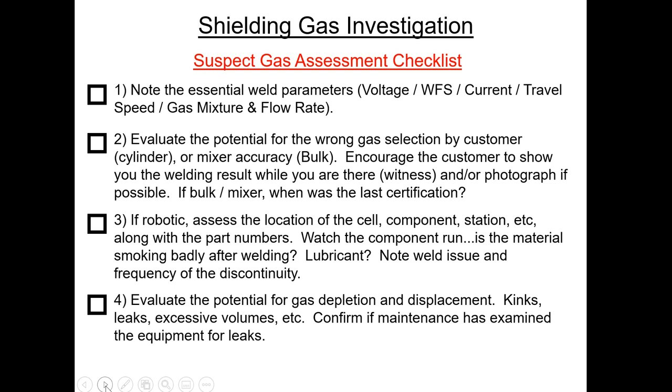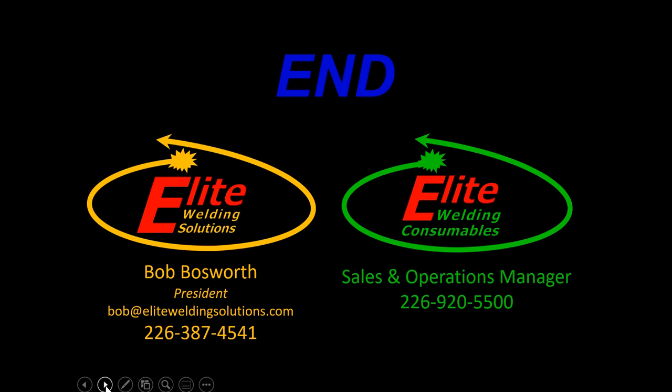And keep in mind that a leak is not porosity. A leak is a lack of gas, which could lead to porosity. But air cannot get back in, cannot defeat the pressures that are on the other side of your shielding gas system. So don't believe it when some people say, well, there's a leak of gas there, so probably air is getting in. No, we only live under 1 bar in this world, and that's about 14.7 pounds per square inch. There's pressure here, but it's not enough to overcome the 30 or 50 pound pressure that you have inside your piping system for your shielding gas.